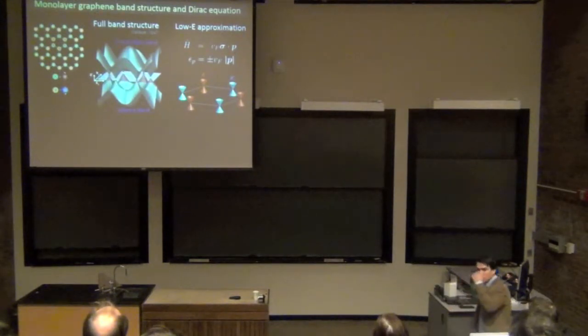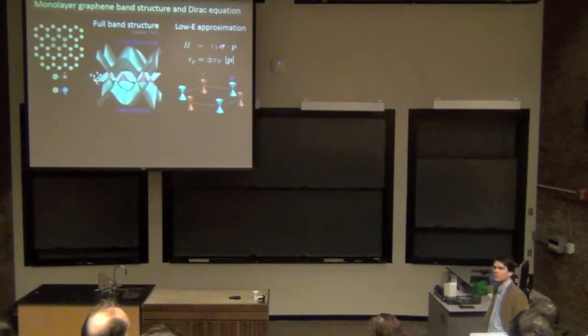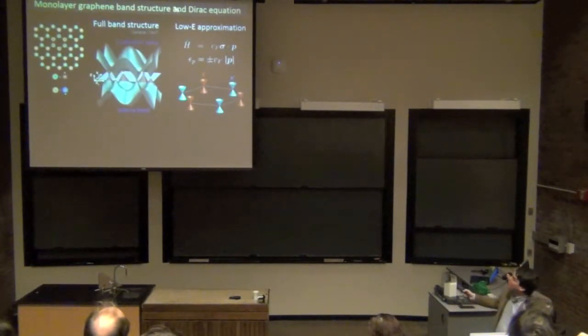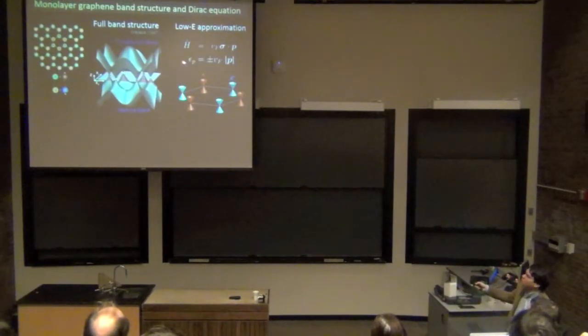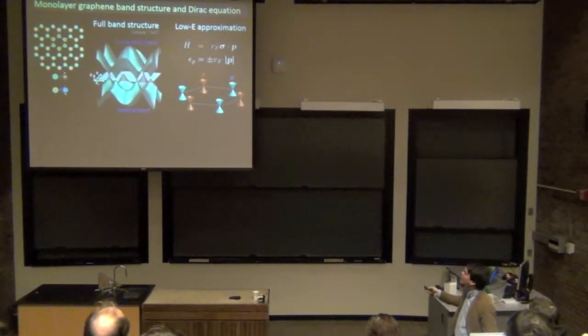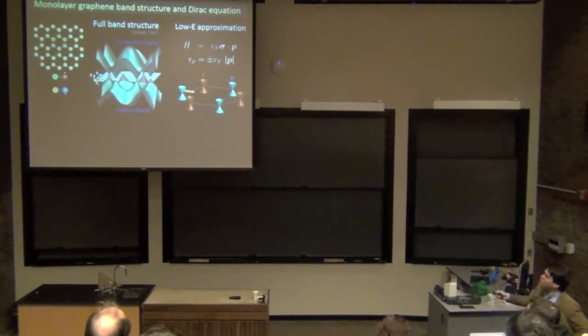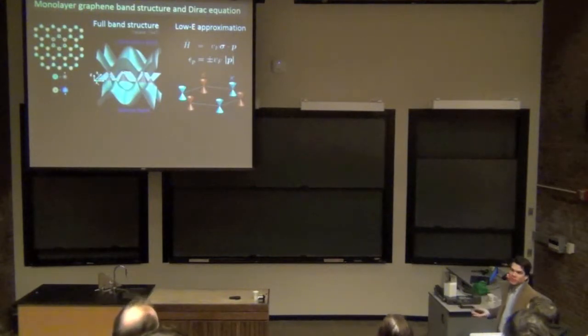And if you zoom in at low energies here, what you find is that the appropriate Hamiltonian to describe the excitations in this system looks an awful lot like the Hamiltonian that was written down almost 100 years ago by Dirac, where the energy of the electrons is actually proportional to the momentum and not to the momentum squared. So what that tells you is that the electrons in graphene behave as if they're relativistic particles. They basically behave like photons with no mass and traveling with a velocity which is a fraction of the speed of light. So this is really exciting from a condensed matter physicist point of view, because you can essentially study the relativistic dynamics of electrons in a solid state system.